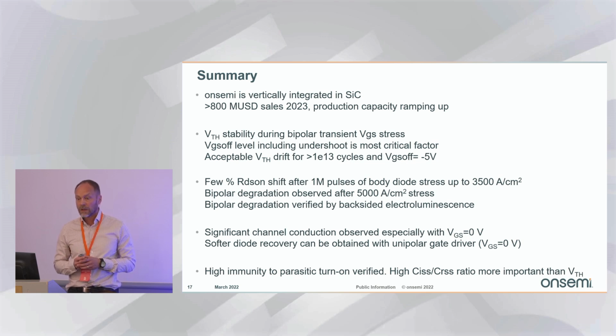On the bipolar degradation, we have a few percent RDS on shift for body diode stress up to 3,500 amps per centimeter square. But we can see some clear bipolar degradation after 5,000 amps per centimeter square, verified by electroluminescence, and then significant channel conduction with VGS 0 volt. And the recovery can be obtained using a unipolar gate driver with 0 volt VGS. And high immunity to parasitic turn-on was verified with a CISS to CRSS ratio. And thank you for your attention.